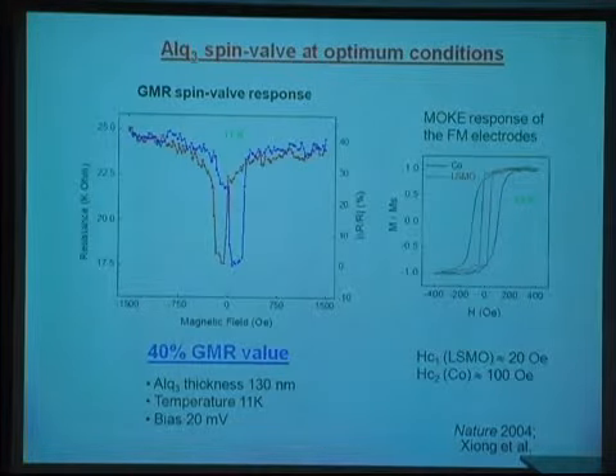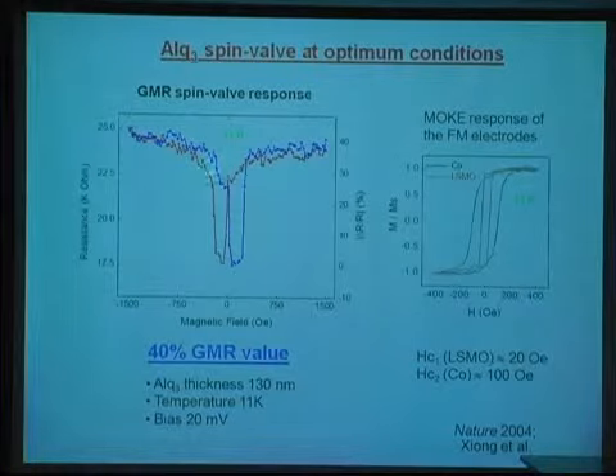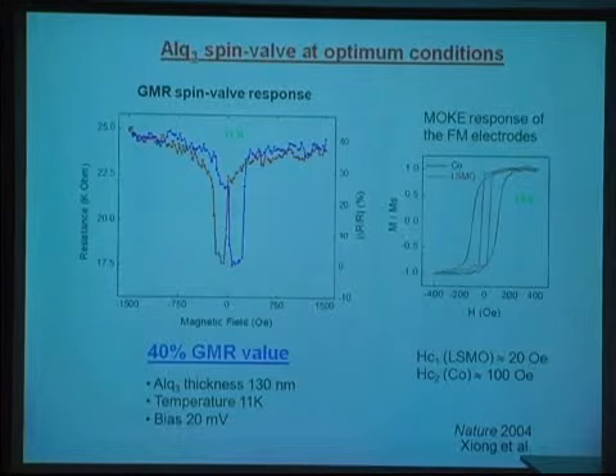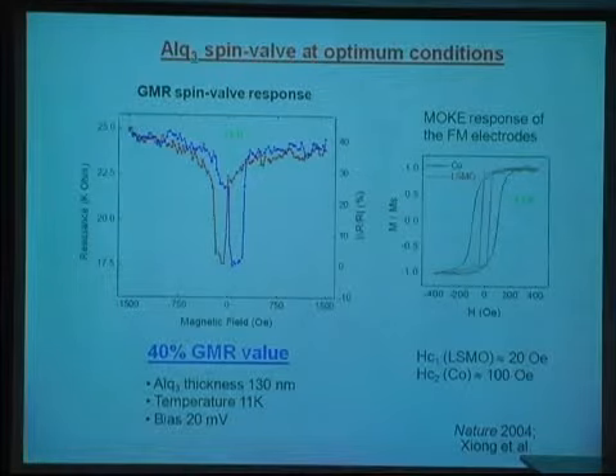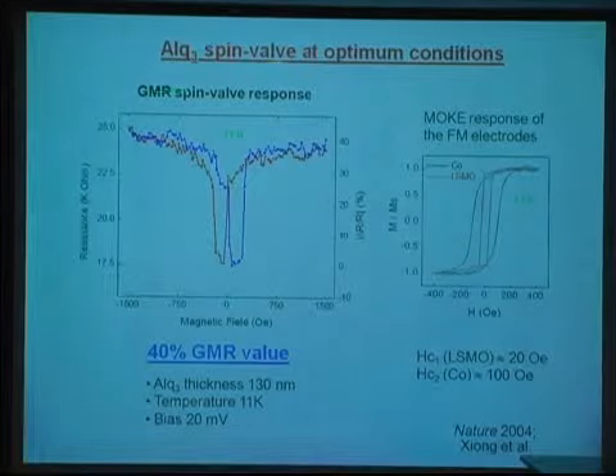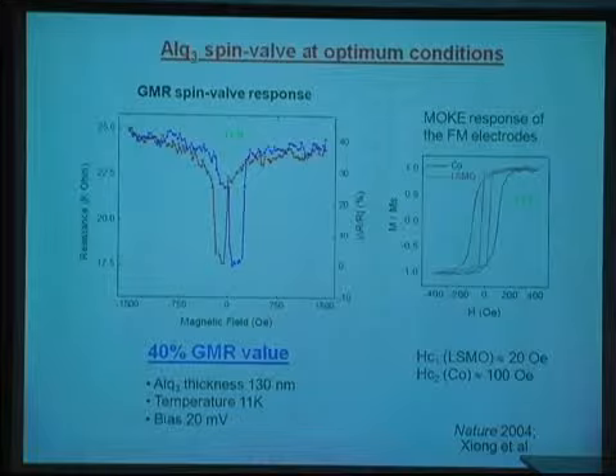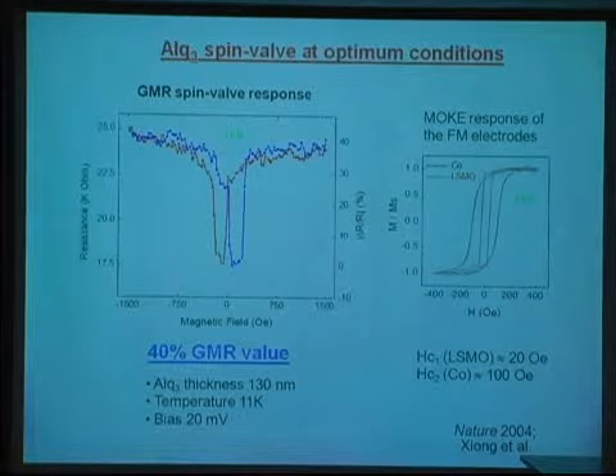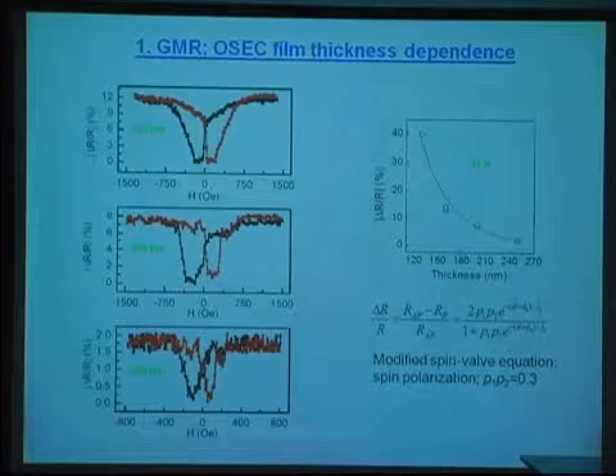Okay, so the magnetoresistance in the previous device was reported in 2004 in Nature from the Vardeny group, about 40% at low temperature. At this time they claimed giant magnetoresistance, which means they claim that the effect is related to spin injection and spin transport inside the organic materials. Okay, so here is some result of the thickness dependence.